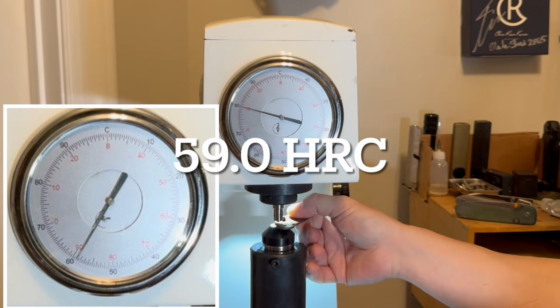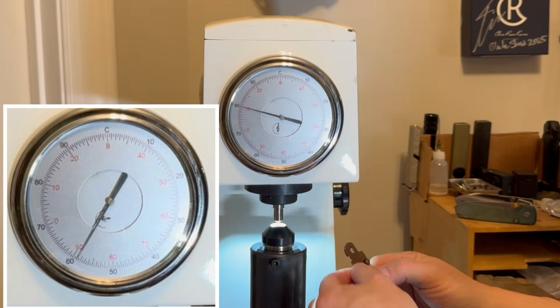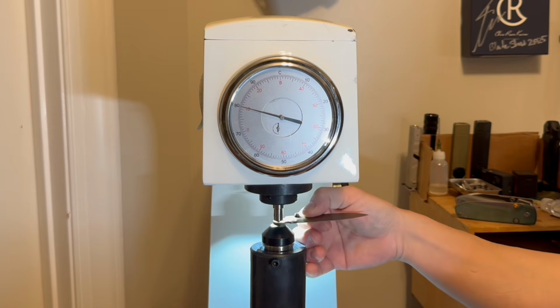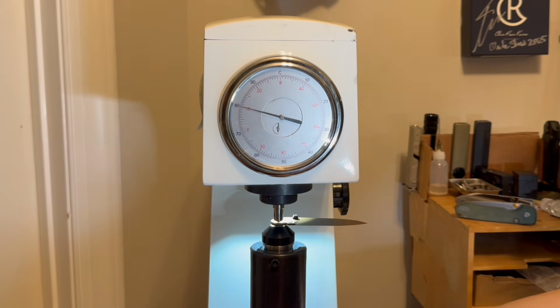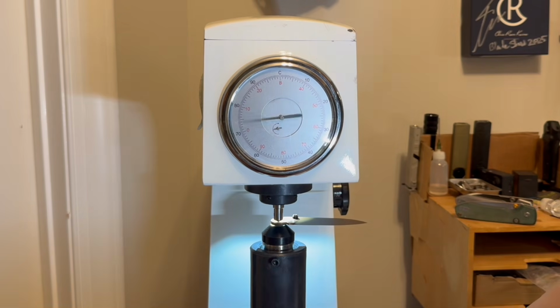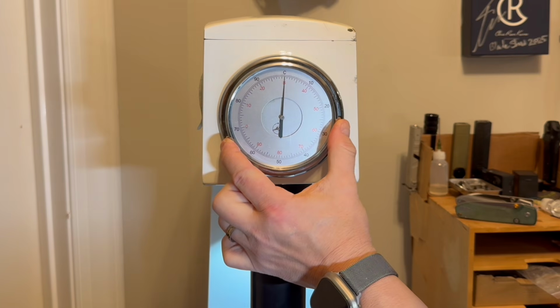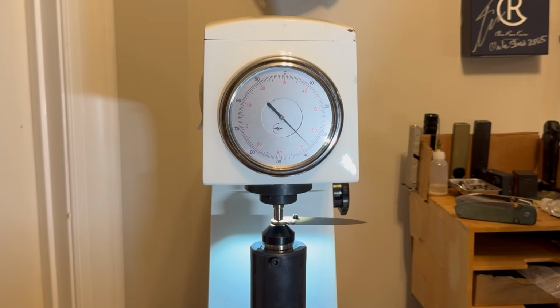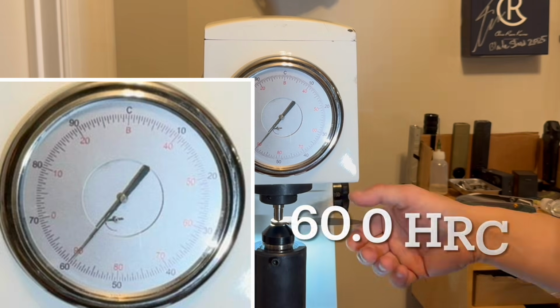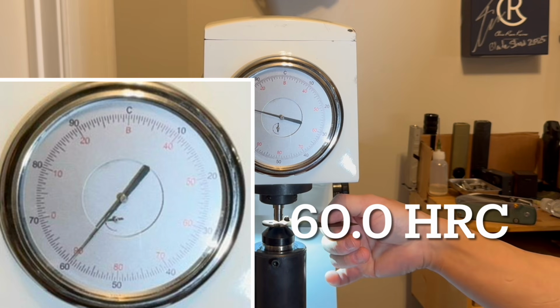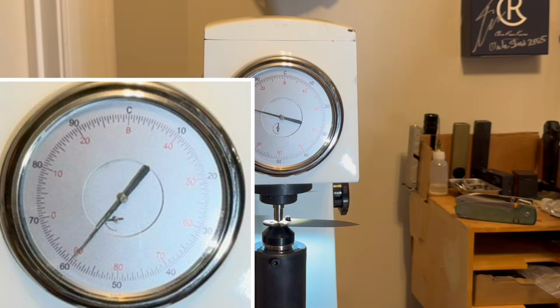59 HRC on the second poke is a surprise. I usually don't see such a gap between two pokes. And looking at the blade, I realize I poked it a little too close to the bearing recess. So I'm going to redo, and this result will get thrown out. Let's talk about 154CM steel. But first, the second legible poke result is 60.0 HRC.